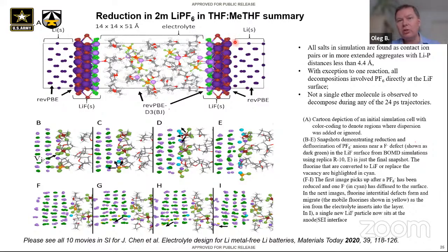What should be included is grain boundaries between different SEI components, but it's harder to do because here we need to choose the lithium dimension in such a way that it would conform to the LiF on the length scale without having much strain on either of them, because then lithium starts buckling. And Travis has gotten good lengths to find this good match, right? So now think if you have 2 components, it becomes even harder unless you have an amorphous soup. If you have an amorphous soup, that's a good question what happens. So that, I guess, is the best short answer I can give.